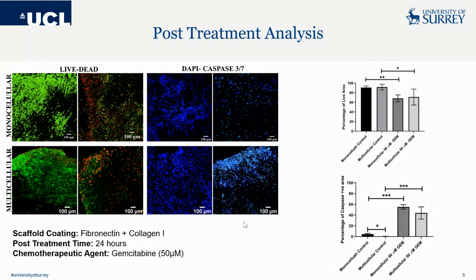Post 4 weeks of culture, we treated them with 50 micromolars of gemcitabine. This particular concentration of the drug was selected based on our previous publication. If you are interested, we can discuss it later. We then did a post-treatment analysis 24 hours later, which included live dead analysis, as well as checking for the presence of apoptotic marker, which is caspase in this case.